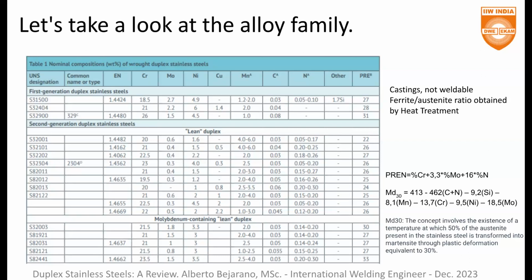Okay, heat treatment that is quite simple for a casting, but almost impossible in practical terms for weldments. Because normally this heat treatment implies raising the temperature up to 1000 Celsius degrees, and it could be economically impossible to treat each joint in a weldment. Okay.